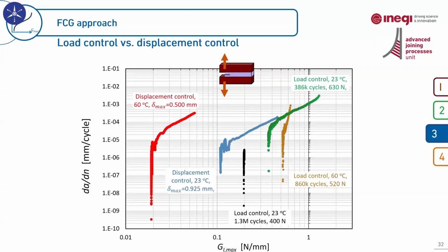We have analyzed this parameter on adhesive joints, and we noticed that the choice of test method can lead to significantly different results for fatigue crack growth in adhesive joints. Our results for a polyurethane adhesive showed that the threshold fracture energy obtained based on displacement control is a bit lower than the threshold energy obtained based on a load control strategy.